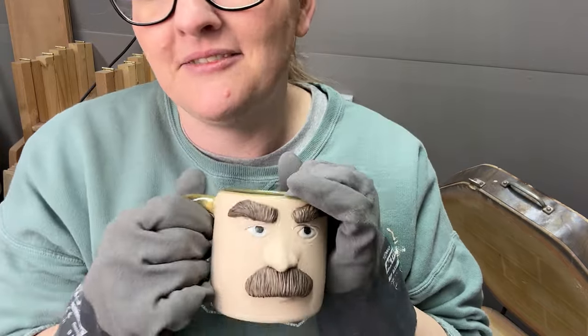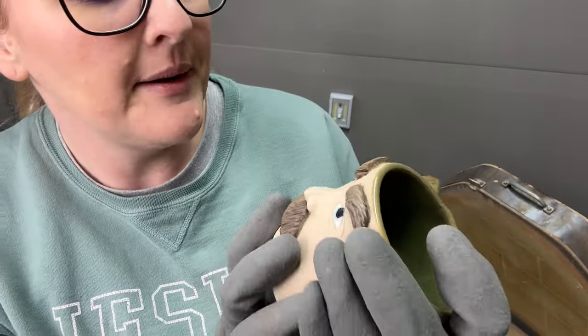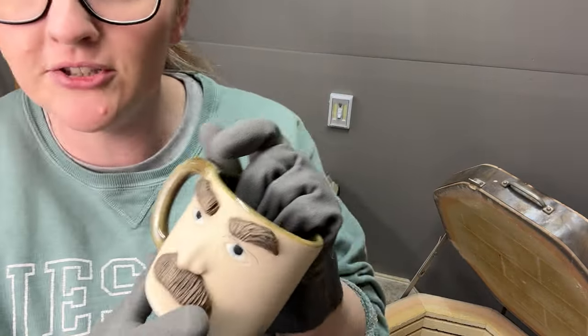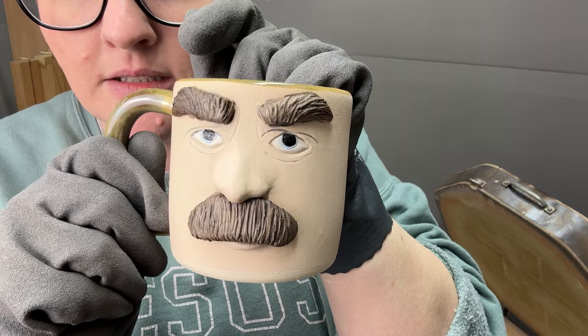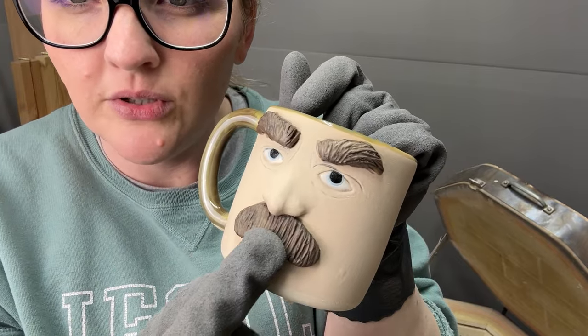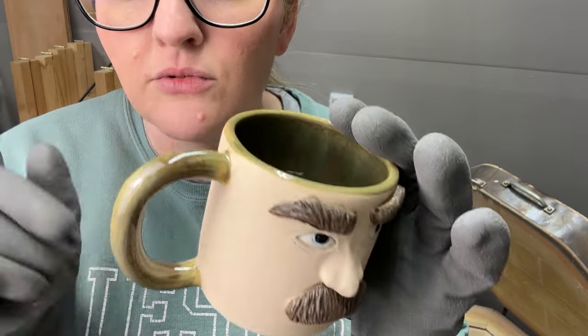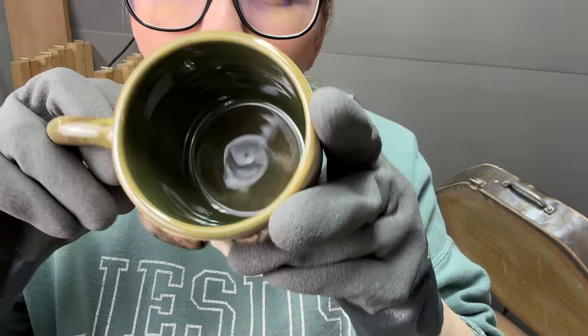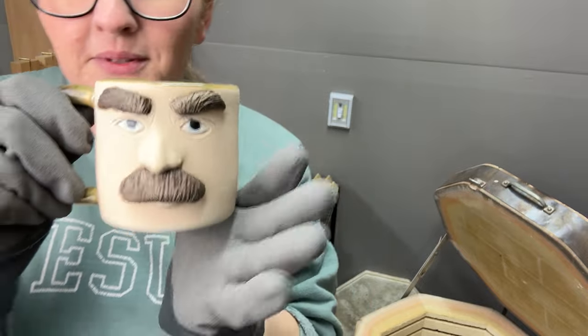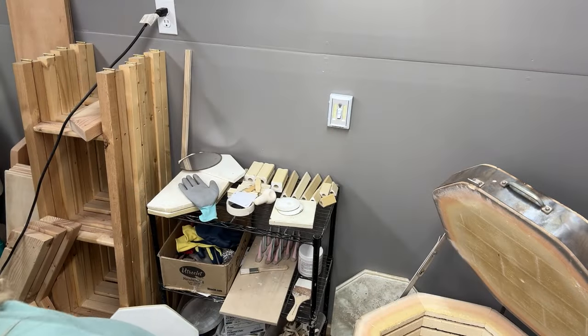Some dad is going to get an amazing Father's Day gift. I did two different kinds of brown on the two guys. This one is leather — it looks really good — and I kind of think I should have done leather on the other one too. I did black underglaze first, wiped it back, and then two coats of leather. Cocoa underglaze, then two coats of seaweed on the handle because I didn't want drips, and three coats of seaweed inside.